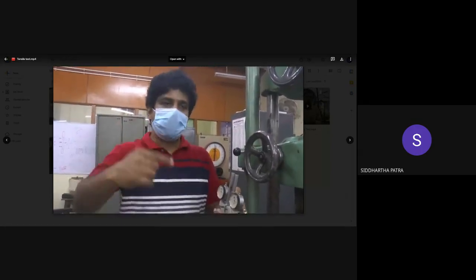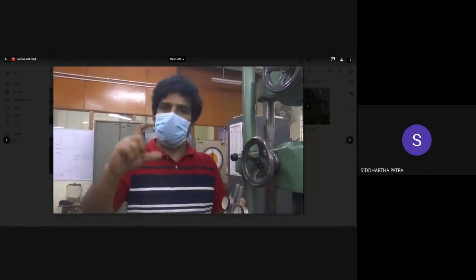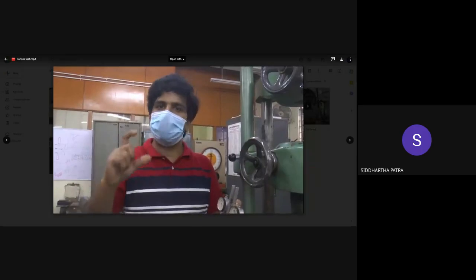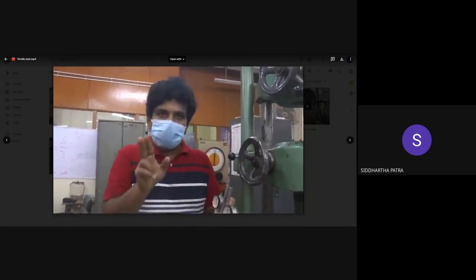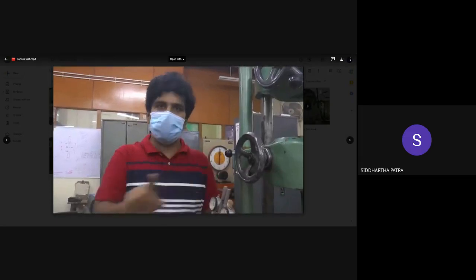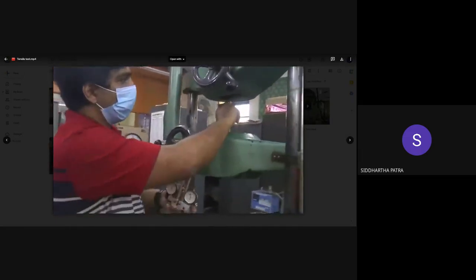And actually, the test that we are doing is suitable for a uniaxial stress state. So we are doing an analysis with a uniaxial stress state. To ensure a uniaxial stress state happens in the region of the bar, we are supposed to take 1/3 of the total length. Now the total length is about 180 millimeters, around 160 to 180 millimeters.